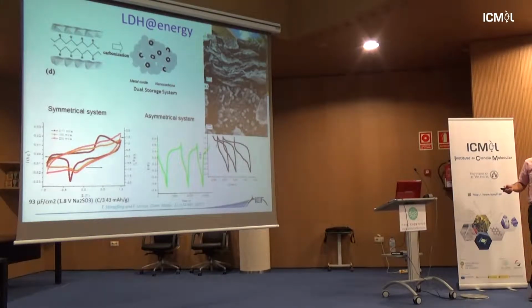And when you go to a very high speed of cycling, like 200 millivolts per second, so it's very rapid, you get rid of the Faradic, but you keep the capacitive behavior. So you have a dual system, very demanding in terms of power, but you keep some energy as well. So that's been done on this kind of system.